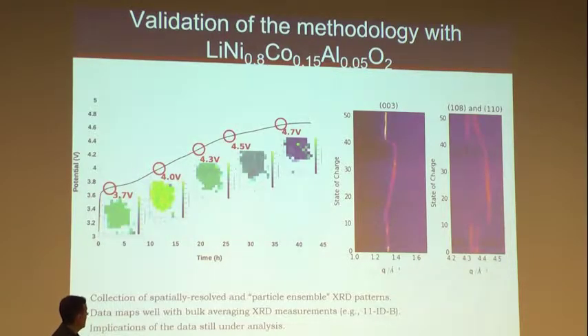This is the data. Again, this is data that literally was just given to me last week, where we can resolve the particles being oxidized, and then we can also do the same thing that I did before, where we integrate the overall diffraction pattern for the whole particle, and we can see the diffraction peaks evolving as the lithium is being removed. These are evolutions that look very similar to what you get in a bulk diffraction experiment, but we're still comparing the details to make sure that everything looks pretty much the same.